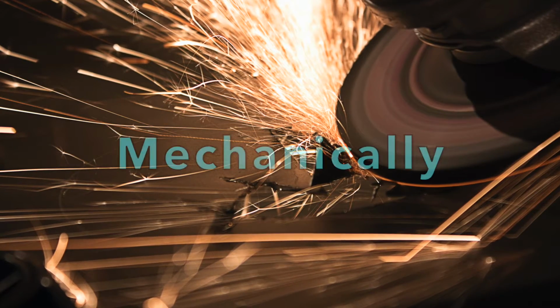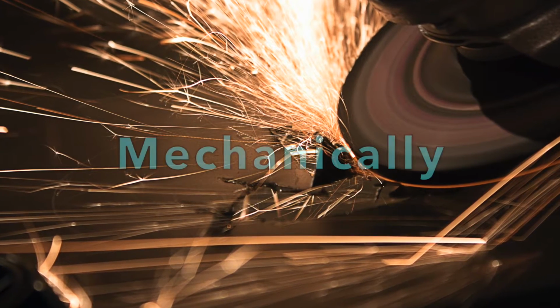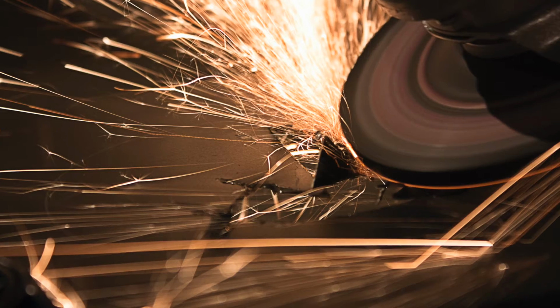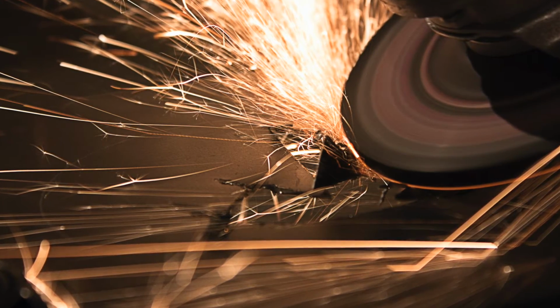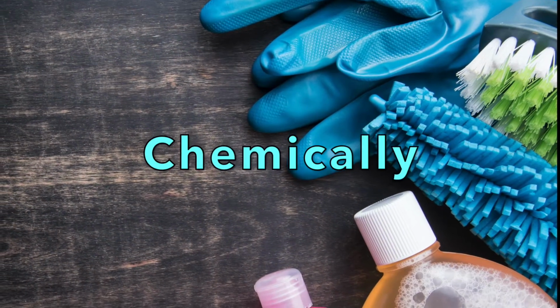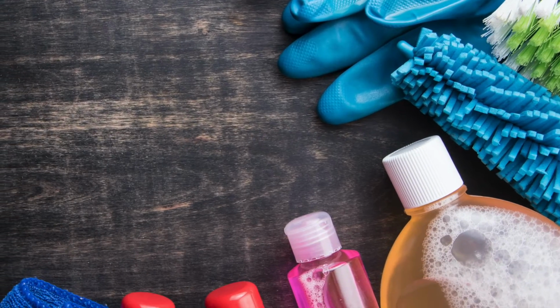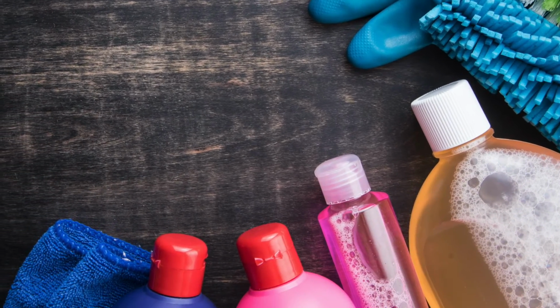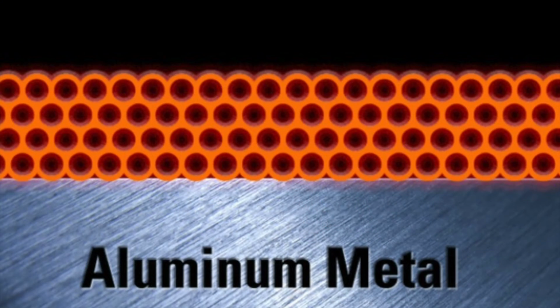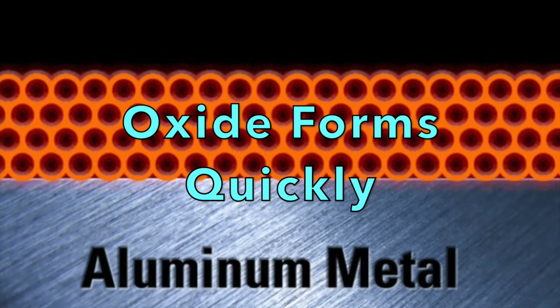Cleaning can be done mechanically by a wire brush, grinding, scraping, machining, sandblasting, or filing. Chemical cleaning may be done by using alkalis, solvents, detergents, or acids. It is important to weld on aluminum right after you have cleaned it because the oxide layer can form as quick as 10 minutes after cleaning.